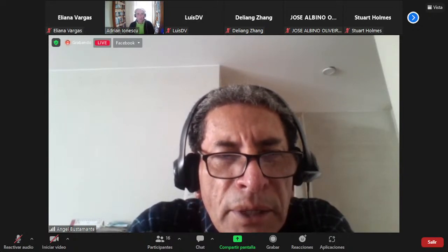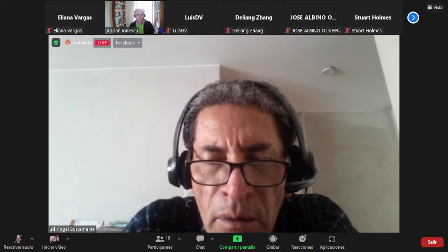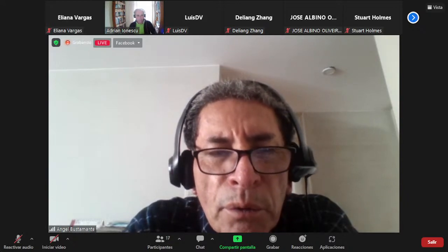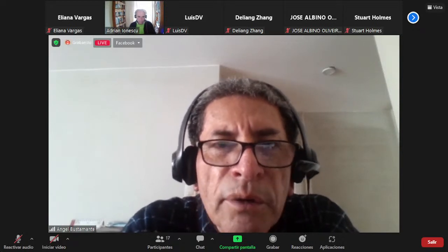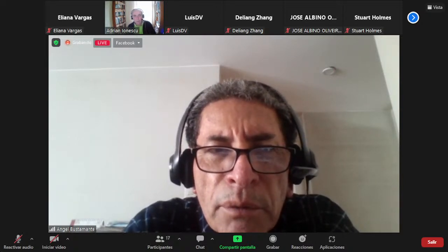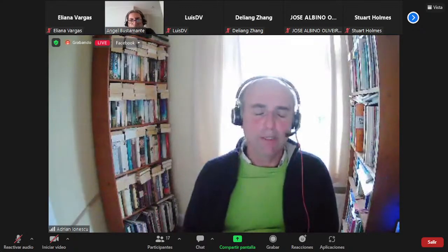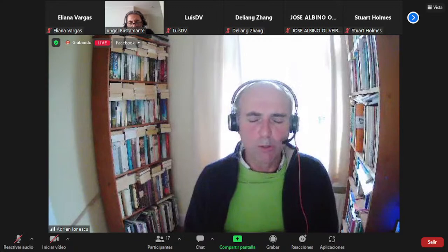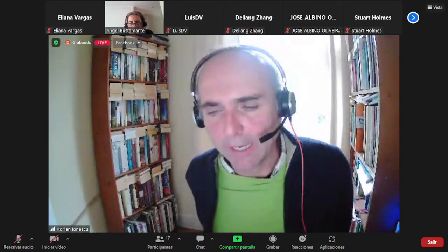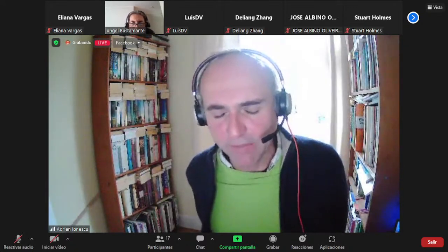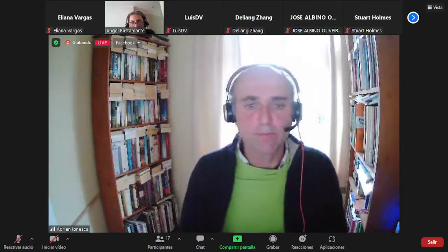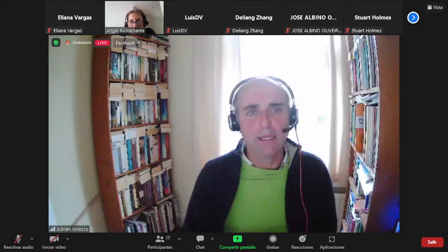I think my question is about the critical temperature in your superconductor diode. It's about 5 Kelvin or 10 Kelvin, I don't know the temperature. 5 Kelvin. I'm not very familiar with this, but there is niobium, and depending on the thickness of the film, it alters its critical temperature. So if I remember correctly, the 8 nanometer film has about 5.25 Kelvin. That is my understanding. So it's not bulk behavior. I think it's slightly higher in bulk.